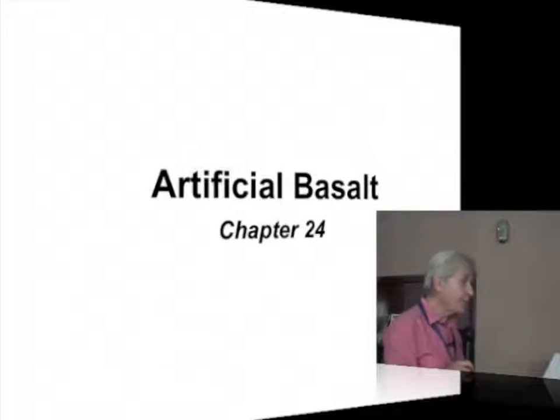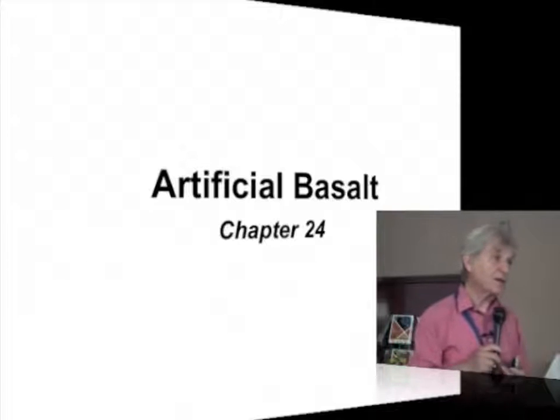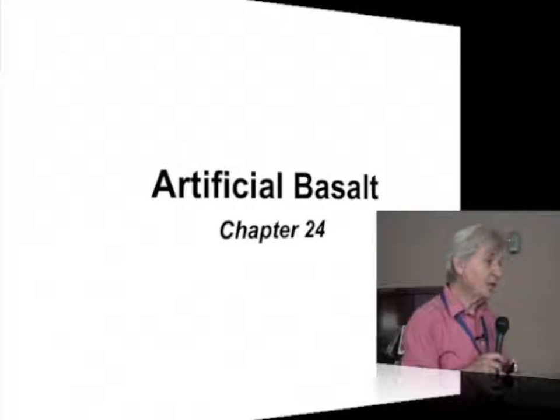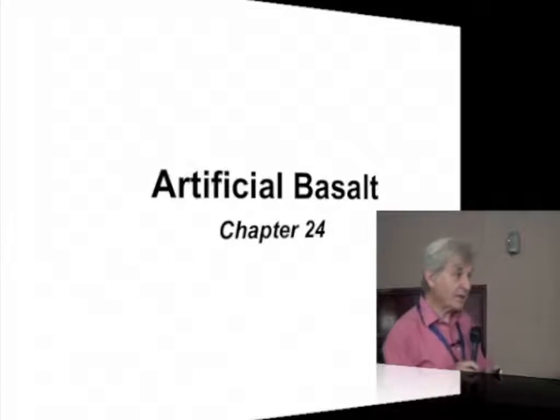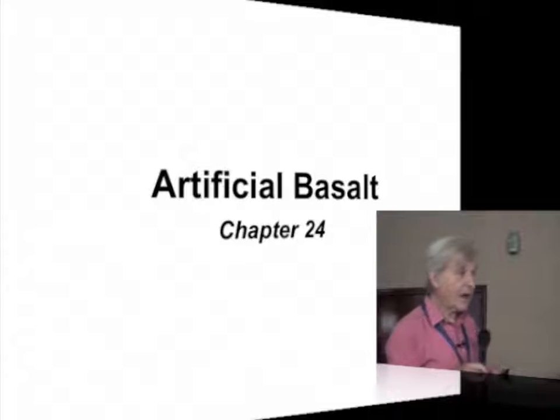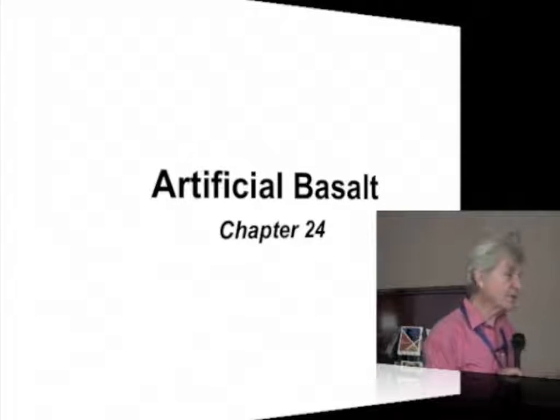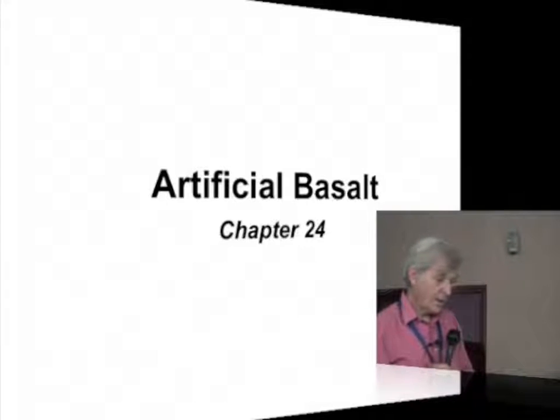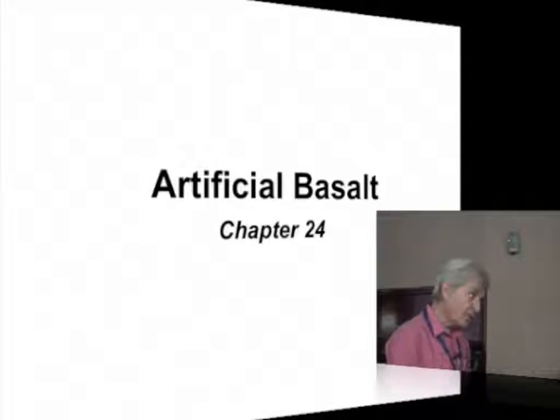The system that we have experienced is what I call the artificial basalt, which could be alkaline slag. Instead of having calcium slag, we have alkali slag, and from a geological point of view, it is a basalt. This is in chapter 24 in my book, and I sum it up very briefly. So we manufacture a basalt at 1200 degrees C, 1250 degrees C, or 1300 degrees C. That is to say that manufacturers are accustomed to and go through the furnace route. We don't change anything, just the raw material is different.